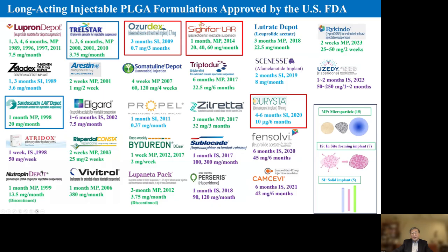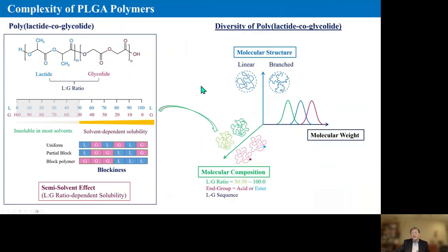Currently, there are 27 FDA-approved PLGA-based formulations, and some of them are really complex. For example, Sandostatin LAR is made of a glucose-star PLGA polymer, which has been difficult to characterize, but only after FDA tried to figure out how to assay them, we developed the method. Also, Trelstar contains more than one type of PLGA, which also makes the analysis a little bit difficult. But again, we were able to develop a new method because of the FDA initiative. Now, Ozurdex and Durysta are two ophthalmic formulations, and they present another difficulty because of their small size. I will talk about that in the next slide. Sandostatin LAR is not a mini-size, but because of the composition of the PLGA in the formulation, it presents unique challenges. So we'll talk about this in the next slide.